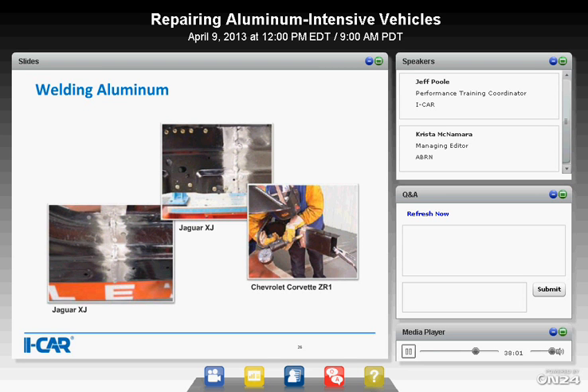At one point in my career, we got a bottle of shielding gas that unfortunately wasn't so pure, and thankfully during the test weld process, I identified that, hey, we're getting porosity in here that just isn't going away. Let's go exchange the bottle, and we got a new bottle of gas, and we didn't have that issue anymore. So it was good that we didn't experiment on the vehicle. We were experimenting on our test samples, and we found we had an issue.